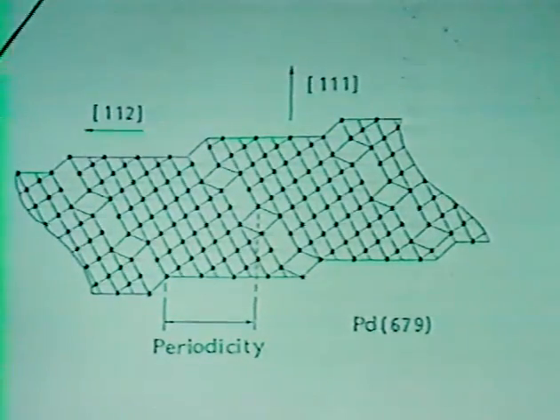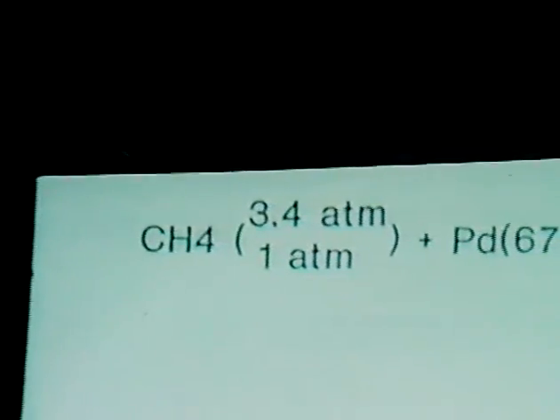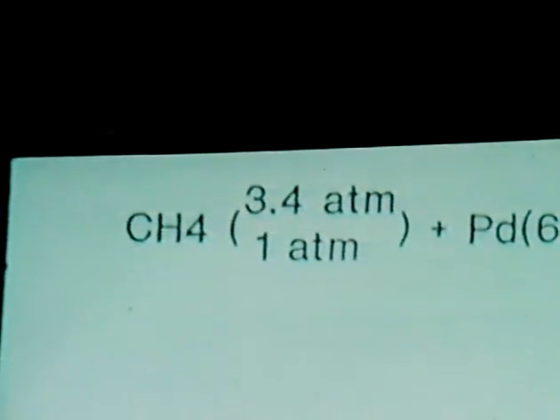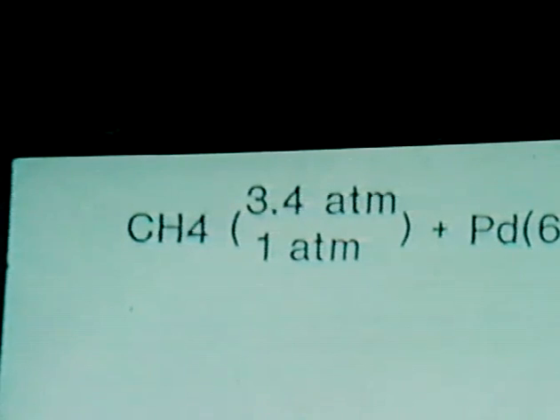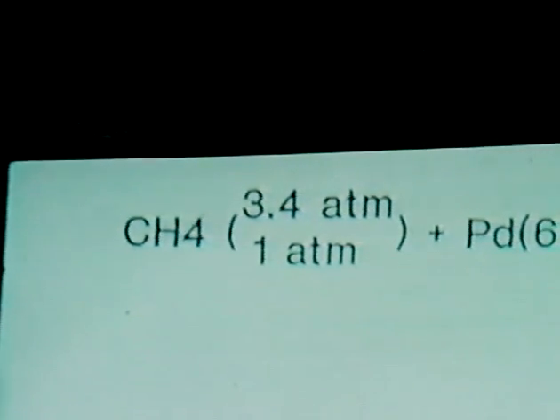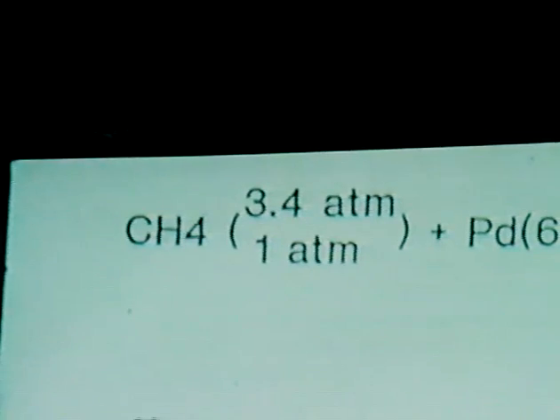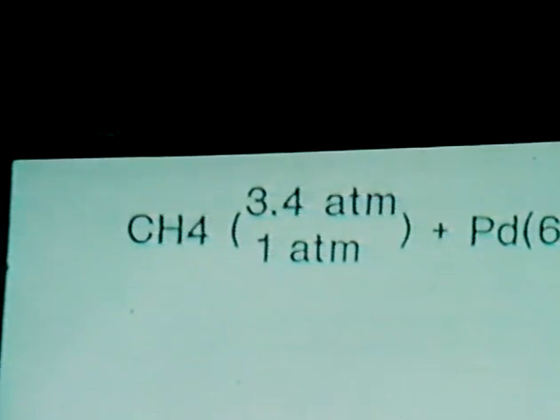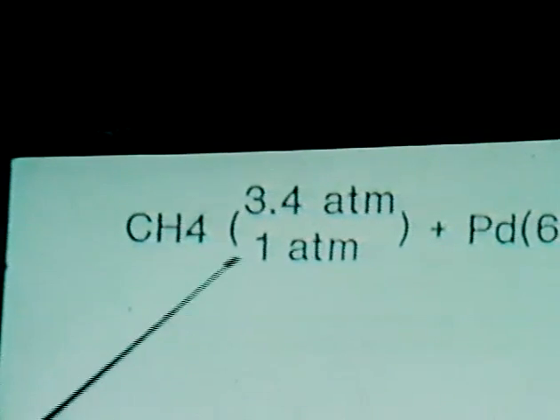And what happens with methane on this particular plane is that at low pressures, at this usual single crystal steady pressure, 10 to minus 6 torr and lower, nothing happens to methane ever. Nothing. Even on a catalyst that looks much more perturbed than these. But by the time one increases the methane pressure to 3.4 or down to 1 atmosphere, one actually cracks the carbon-hydrogen bond on palladium of this type at room temperature. Everything that is cracked remains on the palladium. Nothing goes at that room temperature into the gaseous phase.